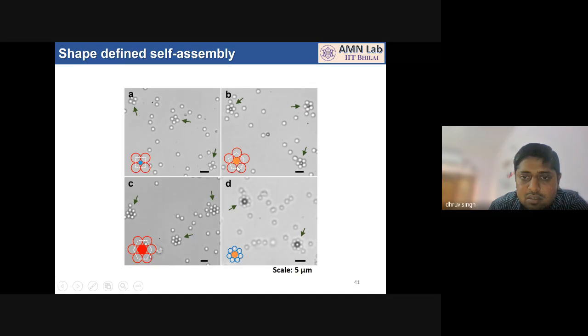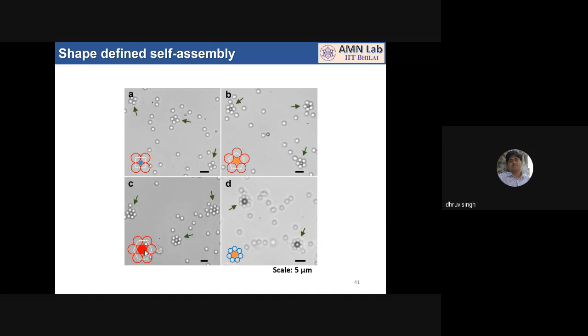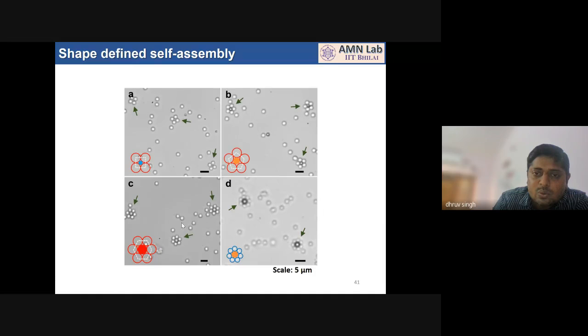If you reduce the size, then this periphery will reduce. So you cannot fit 5 particles. Then you will end up with 4. And if you increase the size of the inner particles, then you can fit more in the surrounding. So this is how the structures are governed. Right now these structures, you can see, are shown by these arrows. These are the structures. They are formed.